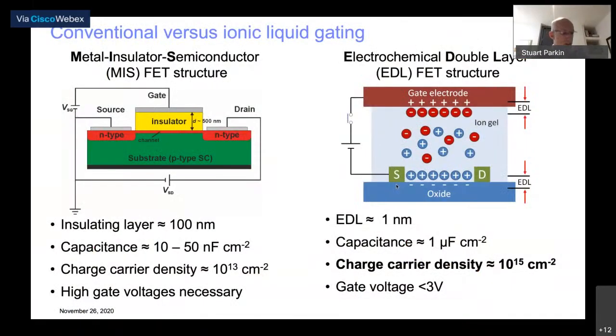Now, if there is a few more moments, I wanted to briefly mention, in the last 3 or 4 minutes, one other aspect of the work we're doing, which is a very interesting concept of using ionic liquid gating to create spin textures using the very large electric fields that ionic liquid gating develops. So you're all familiar with a field effect transistor shown on the left. You have a gate insulator across which you apply voltage to develop electric fields that introduce charge into a channel. On the right-hand side, you can see we replace the conventional dielectric, let's say hafnium oxide, with an ionic liquid consisting of large organic molecules, half positively charged, half negatively charged.